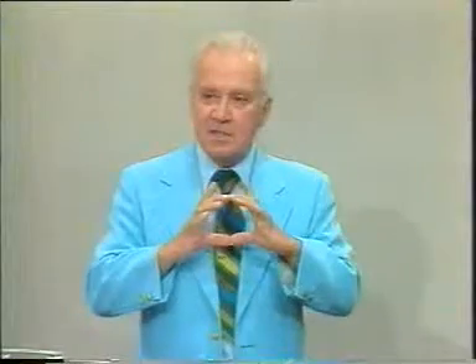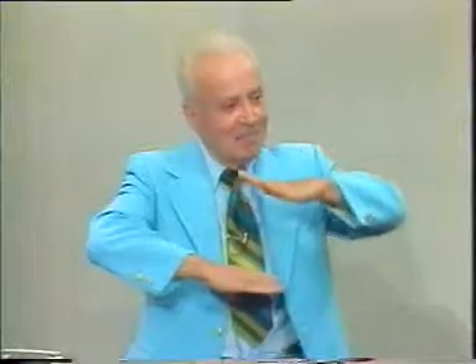Well, what they'll do is they'll take a cylinder of the base material, the springy material, the strength material, and they fit over top of it. It may be a bar, say 2 or 3 inches in diameter, and they'll put a sleeve over top of it of gold. And they take that particular material and begin to put it through the rolling mill, shaped rolling mills. And they keep on reducing it in size, smaller and smaller and smaller and smaller, and they're just making wires. But they're stretching out the gold, and they're stretching out the steel. At the same time, they're bringing them into nascent contact, and it just welds. It's a beautiful weld. It's a cold welding job.